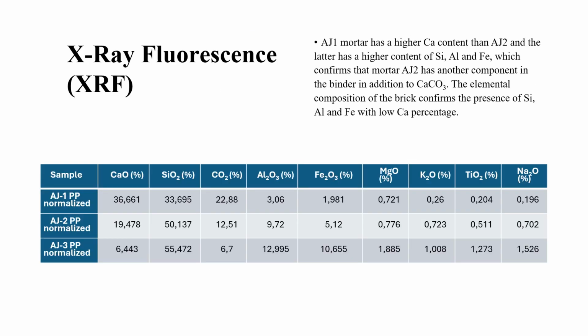In the case of X-ray fluorescence, AJ1 mortar has a higher Ca content than AJ2, and the latter has a higher content of Si, Al, and Fe, which confirms that the mortar AJ2 has another component in the binder in addition to CaCO3. The element composition of the brick confirms the presence of Si, Al, and Fe with low Ca percentage.